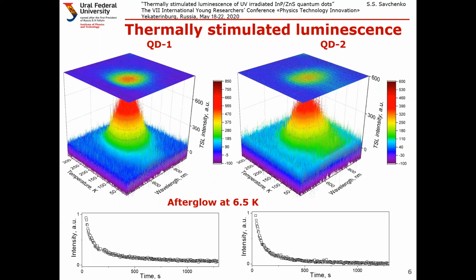The quantum dots are found to exhibit thermally stimulated luminescence response upon heating after irradiation by deuterium lamp during 10 minutes at 6.5 Kelvin. 3D plots of spectrally resolved emission feature one peak for each sample. Intensity has its maximal values in slightly different spectral regions and around 140 Kelvins.